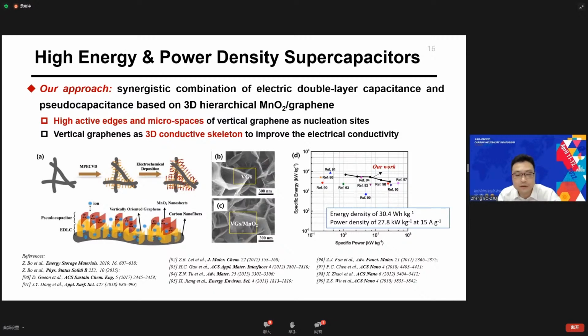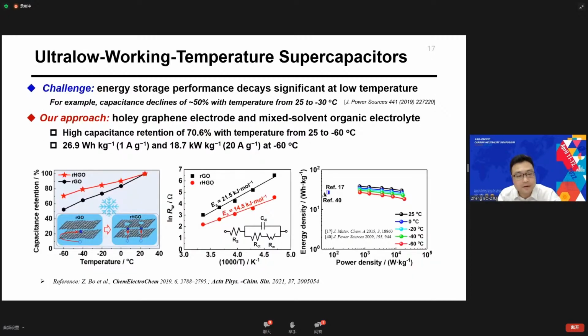Our work achieves this synergetic effect based on some advanced electrode. In our design, the high active edges and micro space of the vertical graphene provide more nucleation sites for the growth of the pseudo-capacitive materials. As a result, supercapacitors with high energy density and power density are realized.